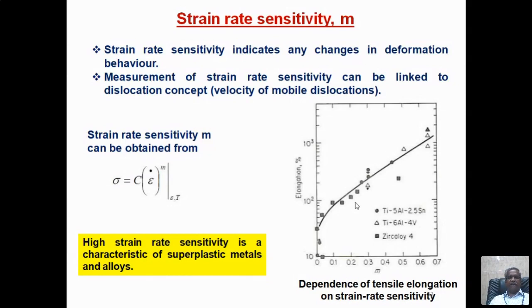So whether a material is sensitive to strain rate or not is very, very essential, because you can apply any strain rate, low, medium or high, and the question is whether the material is sensitive to it. Some materials are highly sensitive, some are less sensitive. Highly sensitive means for a small change in strain rate, the deformation and flow behavior is very different. There are two conditions. One is if you change the strain rate, the flow behavior is entirely different. But if whatever strain rate you apply the flow behavior is almost similar, then it is less sensitive.